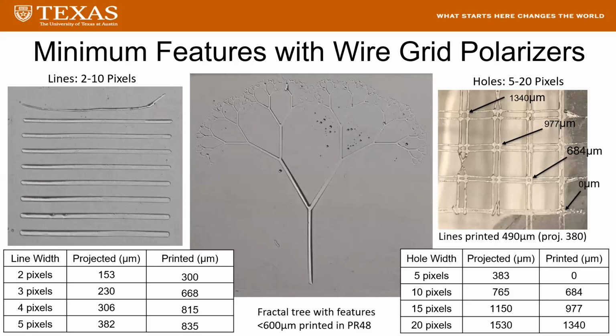These features were cured with an LCD that had the film polarizer proximal to the light source replaced with a wire grid polarizer. This LCD had 75 micron pixels, and we were curing PR48, a relatively easy to cure acrylate resin. We were curing lines ranging from 2 to 10 pixels and holes 5 to 20 pixels. The smallest lines and holes we were able to resolve were 300 and 680 microns respectively. These features were overcured from what we intended, although we were able to get features that more closely matched the intended features when we cured with lower intensities. We just failed to resolve the 2 pixel line at these lower intensities.